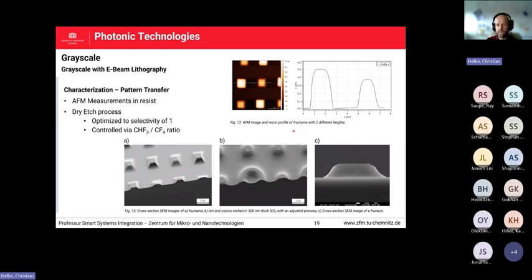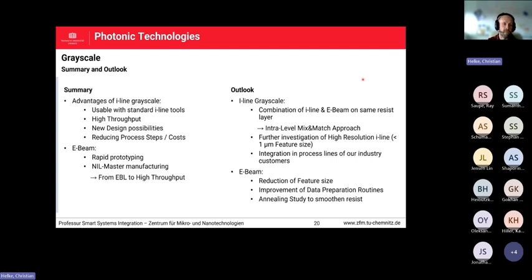This is after etching and after lithography, for example, because the pattern consists of the arranged two different pyramid sizes. You can see the scan here, which really is the same as shown here. And you see here the 500 nanometer height with a certain angle of the side wall. And here with a lower dose, you could resolve smaller structures going to 400 nanometer. So in principle, it works quite well. And we are quite happy to go ahead with many, many more fancy structures and layouts from the colleagues and also from the partners.